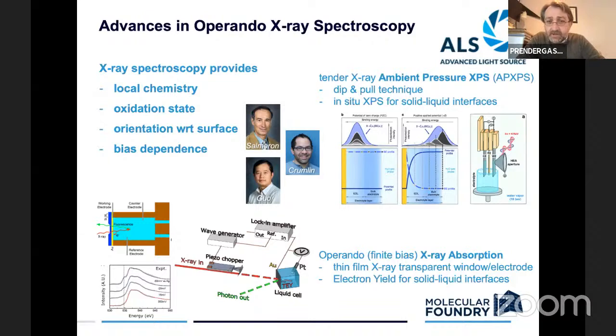The nice thing about these particular measurements, if you do them in a certain mode, which is called electron yield, you can measure details that seem to be within the first 1 or 2 nanometers of the actual interface that you care about, which is really fantastic because that's the typical length scale that we might be able to approach in our first principles calculations using ab initio molecular dynamics.